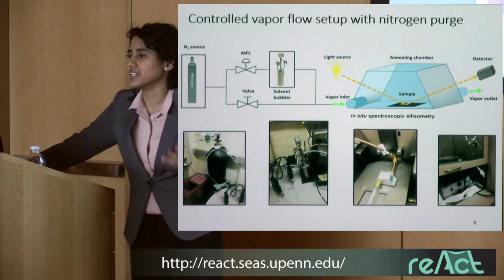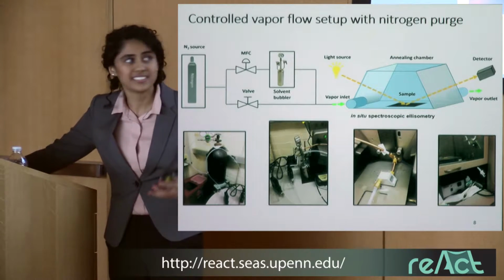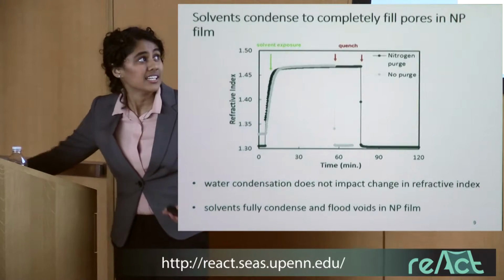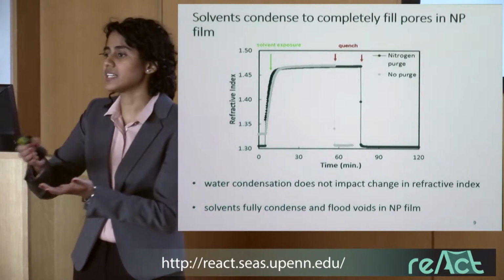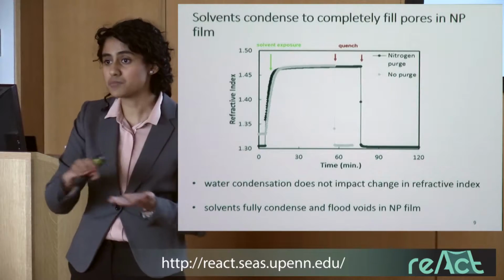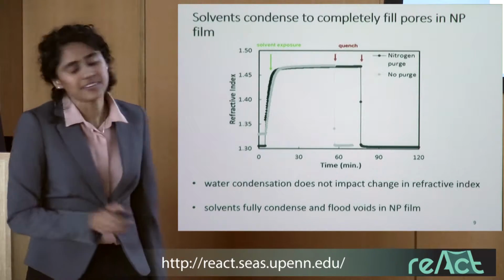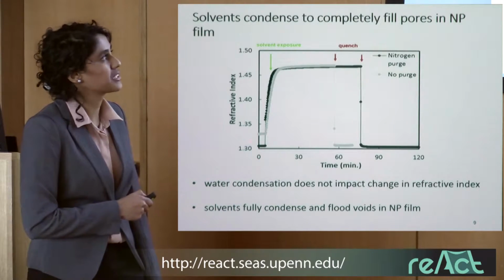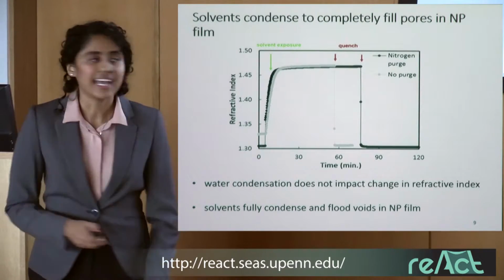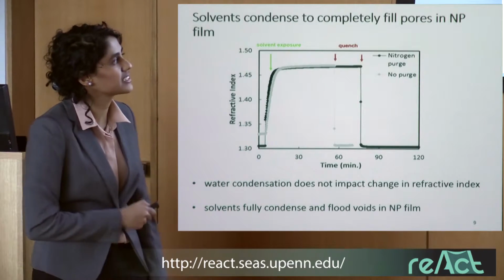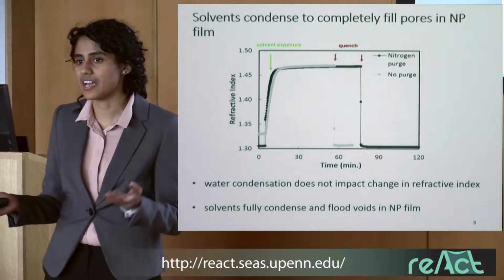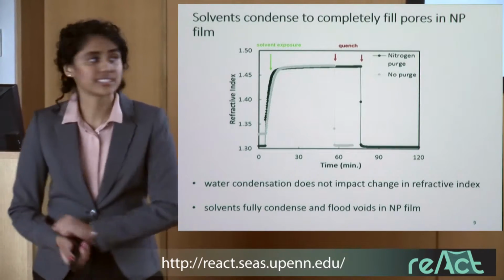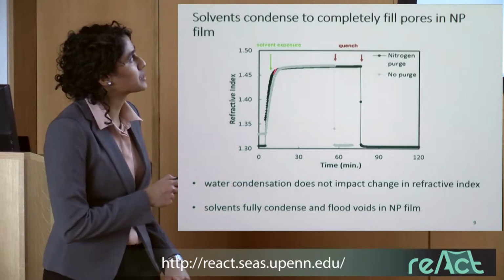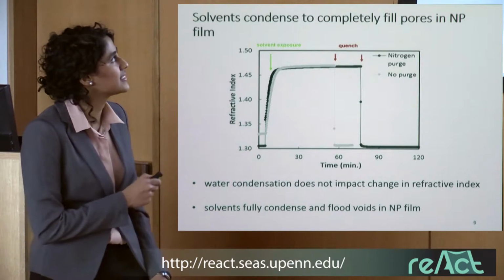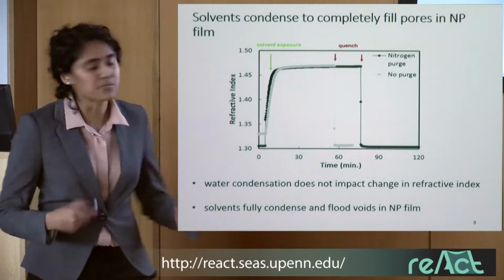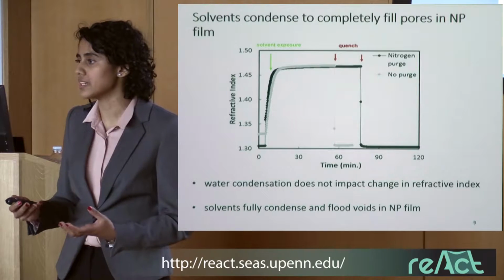So before I started my infiltration experiments, I wanted to do a quick sanity check to see if this capillary condensation phenomena actually occurs. So what I did was, instead of having this bilayer, I just had nanoparticles on my substrate, and I exposed it to solvent vapor. So here I have two different samples, one that's been purged with nitrogen and one that hasn't been purged with nitrogen prior to my experiment. And this difference in refractive index initially basically indicates that in ambient conditions I have humidity and therefore water condensing into my pores. However, when I expose both of these samples to solvent, what I see is that they reach the same refractive index, indicating that both have a similar level of solvent condensed into my nanoparticle packing.